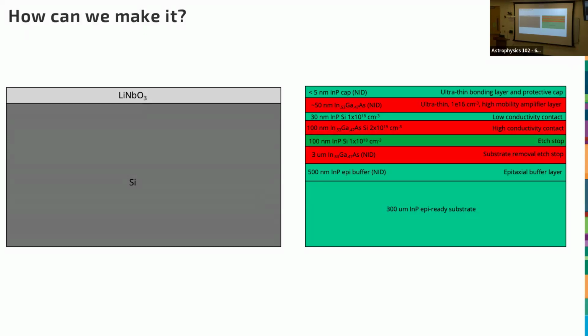Now, why indium gallium arsenide? Why indium phosphide? Indium gallium arsenide is important because it's one of the highest mobility, easily available materials that you can make. It has a bulk mobility of 10,000 centimeters squared per volt second. That number may not be very meaningful to you, but silicon is more like 1,000, 1,400 actually. So it's a very, very high ratio of the velocity per electric field for an easily growable semiconductor material. This red material.